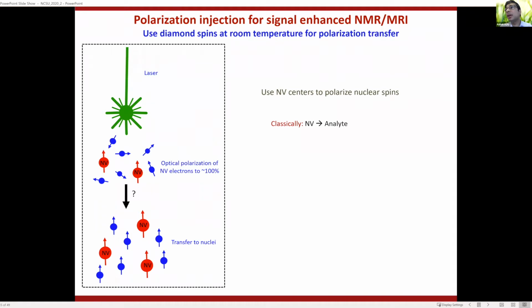But it turns out that these NV centers, although they have very nice properties, come with a very small concentration in the lattice. So they're only about a part per million or so physically in the lattice. So you take a diamond, and that's why they're defects. It's not like the diamond is made of NVs. These are defect centers within the lattice, so they're low in concentration.